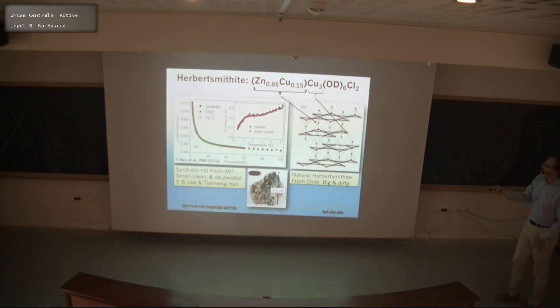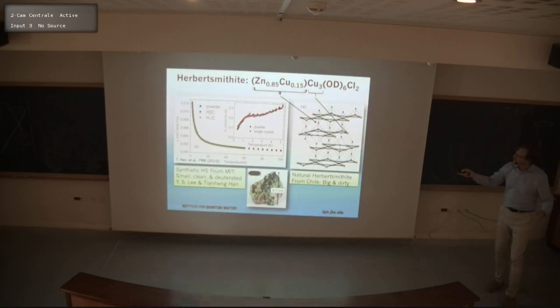One way you see it is that the susceptibility is very, very bland. Here we're talking about a really concentrated system of copper spin 1/2 degrees of freedom with really strong interactions between these, but there's no magnetic order. In fact, no spin freezing or glass formation or anything at all is happening. The susceptibility just comes up in this kind of tail-like behavior. So that's really quite unusual.